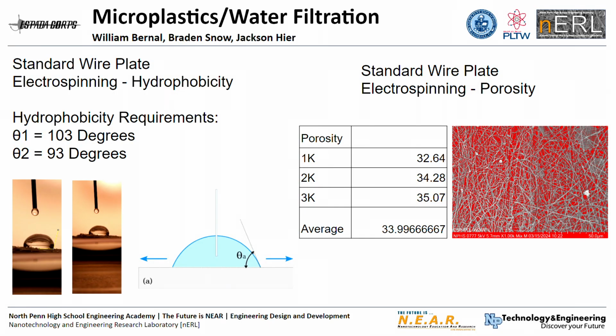There are a couple benefits that come with this. For instance, the wire mesh is conductive. It makes it a little bit easier to harvest the fibers, and most beneficially, it sort of gives the microfibers a pseudo structure to adhere to, which helps with alignment. One of the qualities we were looking for in our filters was hydrophobicity, so they didn't break down in water. The cutoff for hydrophobicity was a 90-degree contact angle with a drop of water on the surface, and we found that our first filter, the wire spinning one, was in fact hydrophobic.